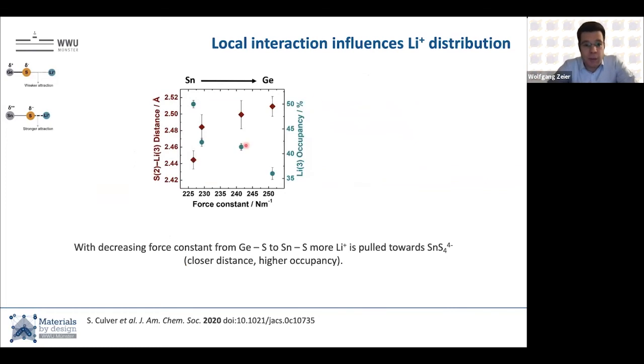Now we can find a few correlations here. We can plot our sulfur 2 lithium 3 distance against the force constant that we can measure, and at the lower force constant, so the weaker tin-sulfur bond, we also find the shortest distance because of the higher electron charge density on the sulfur and the higher occupancy.